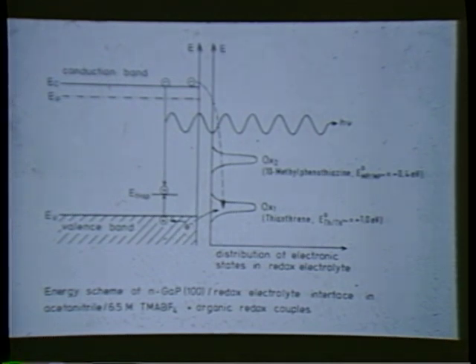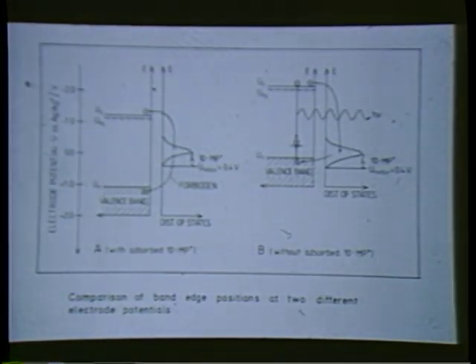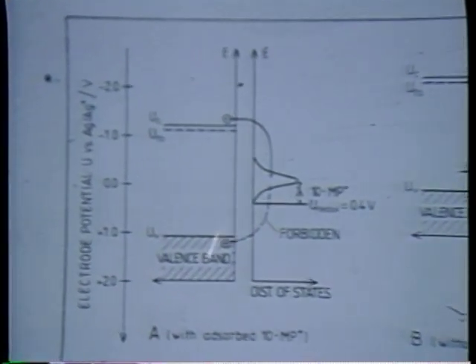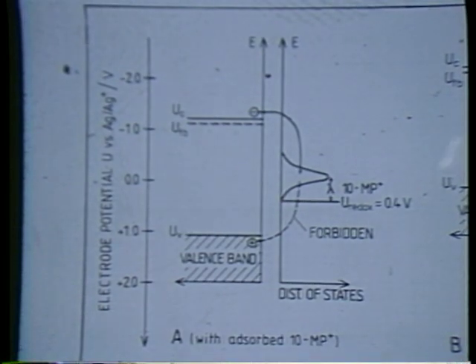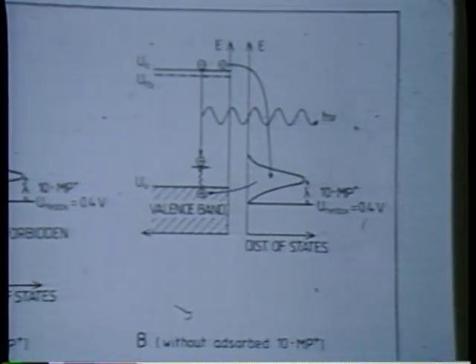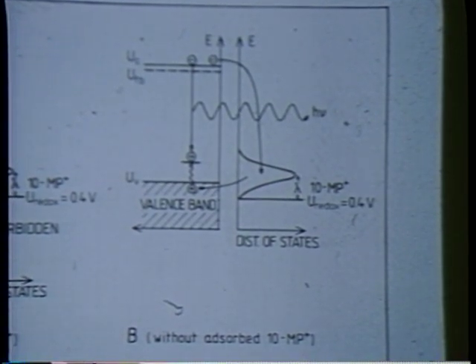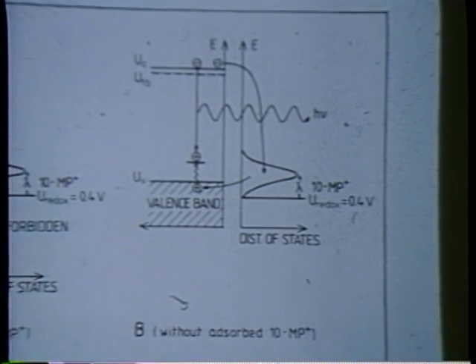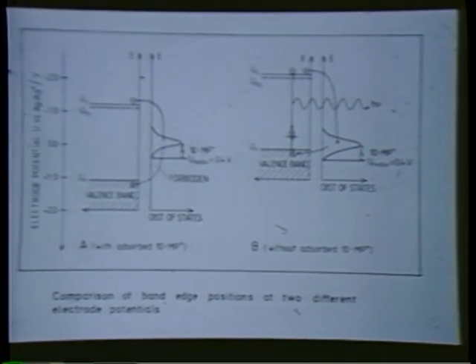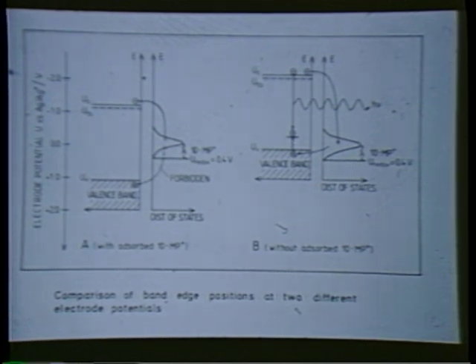We can see luminescence from this redox system only if we lift the bands upwards. And this occurs if we accumulate so many electrons on the surface that now the Helmholtz double layer will be charged. And this shows here the situation. Let the situation at a voltage where we cannot yet inject holes, but by uplifting, that begins, and then we see luminescence. And the voltage drop we need in order to see the luminescence corresponds very well to the difference in the redox potentials. So much about the redox reactions.